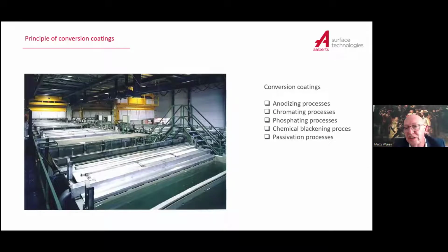Now, conversion coatings: anodizing processes, chromating processes, phosphating processes, chemical blackening processes, and passivation processes, because also passivating of stainless steel is a conversion coating. Because what you do is make sure that the chrome in your stainless steel reacts with oxides of the air and forms chrome oxide. And that chrome oxide, which is on the surface of your part, will protect your part from corrosion. And that's passivation of stainless steel.